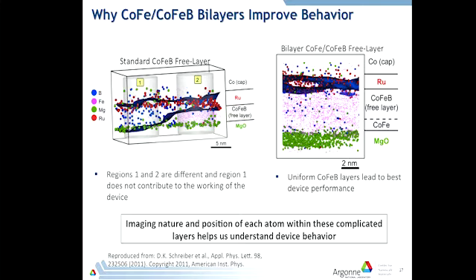And in the not so good sample here, which only had 1 layer, there's more boron here than there is in here. The scale is 5 nanometers, and these are literally individual boron atoms. But as you go across that layer, it's not all the same, it varies. And because it varies, the properties are not very good. But put the 2 layers one on top of each other, and it turns out that what happens is it all becomes nice and uniform.